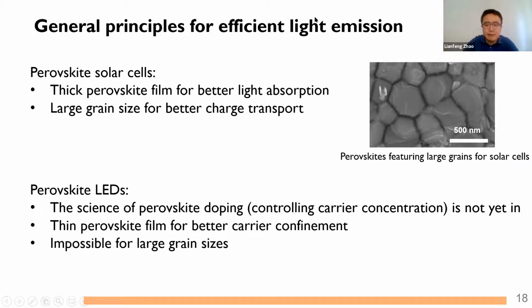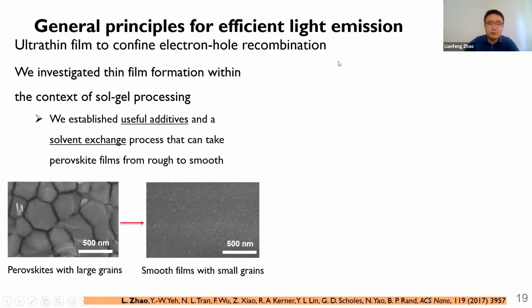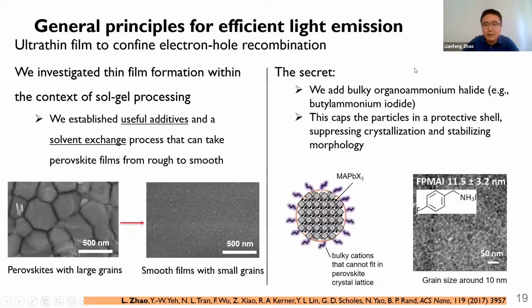But using the established methods developed for perovskite solar cells, it is impossible to keep the device thin, as when the films with large grain size get thinner, there will be a lot of pinholes. So to overcome this issue, we developed a strategy to make the film very smooth with very small grain size. The trick is that we added a bulky organoammonium halide additive into the precursor. And during the film formation process, these additives can prevent the crystal growth of these perovskite nanocrystals. In this way, we were able to confine the grain size to around 10 nanometers. And because of the small grain size, we were able to tune the perovskite film from several tens of nanometers up to several hundred nanometers in thickness.